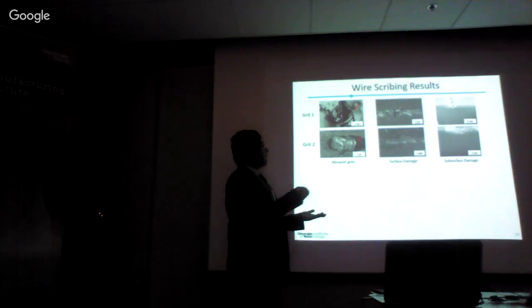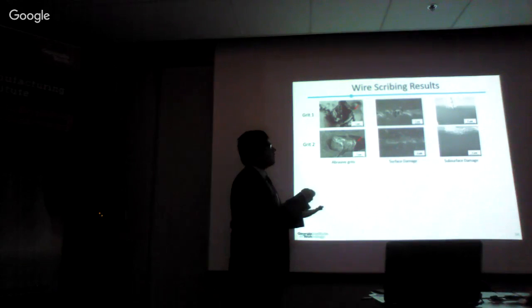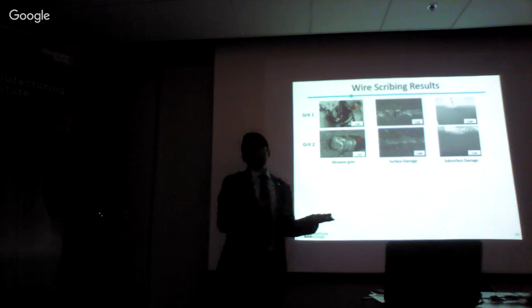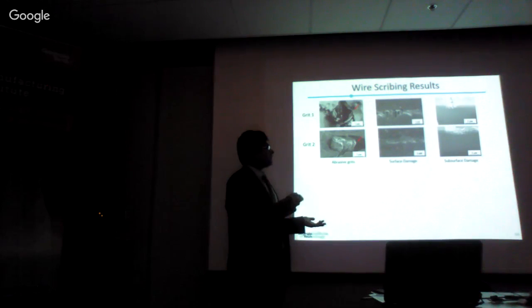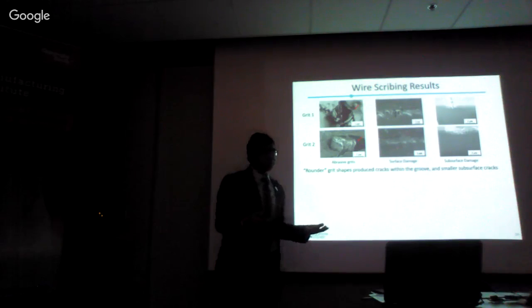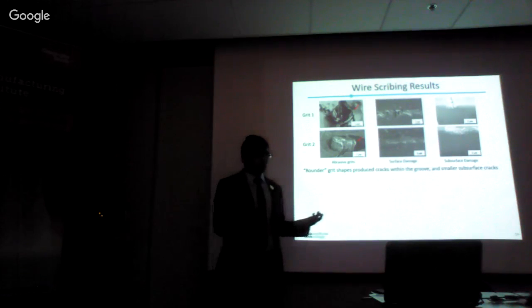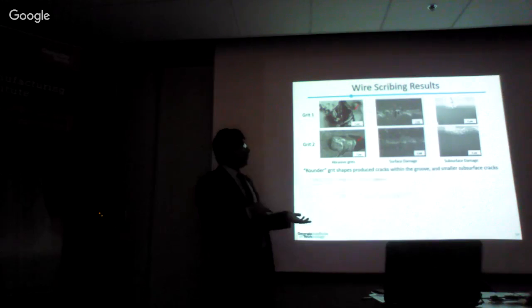If we see the subsurface damage by the FIB process, we find grit 1, which is a sharper abrasive shape, produces cracks at the subsurface, which are lateral cracks because they are starting from the bottom of the groove. This is the groove. And the cracks are starting from the bottom and then curling upwards, and then they will chip off. Compared to that, the rounder shaped abrasives produced not as many subsurface cracks as shown here. So the rounder shaped abrasives produced cracks within the groove and smaller subsurface cracks overall.